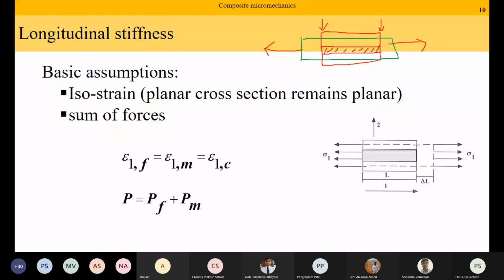Yes? But this line which was straight is going to remain straight. This is because across the length, this geometry is not changing. The fiber is continuous and infinitely long. So we can say the strain in the matrix, which is this region, is equal to the strain in the fiber region. This is your isostrain assumption. This is valid only if the geometry of the fiber does not vary as a function of the length. By length, I mean this is my length. Across this length, if the fiber geometry does not change, then the strain in the fiber and the matrix have to be equal. This is the isostrain assumption.